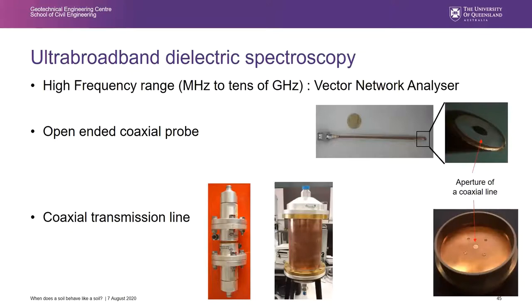In the high frequency range, we've been using the typical vector network analyzer method, which allows us to access the high frequency properties from megahertz to tens of gigahertz. We use a typical open-ended coaxial probe, which is basically just an aperture, a coaxial line which is cut, and the electromagnetic energy radiates into the medium, and based on what is reflected, we can access the electromagnetic properties. We've also been using a lot of coaxial transmission lines.